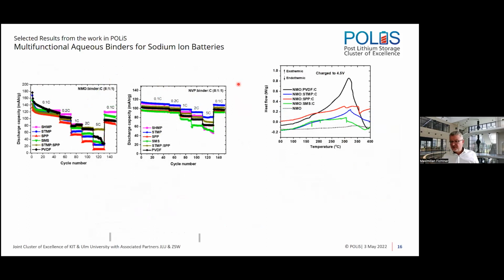An activity which was related to that was the development of new binders, because binders can play an essential role in the performance of batteries. And what we did here was to develop multifunctional aqueous binders for sodium-ion batteries. Multifunctional in that they do not only bind the materials, do not only glue them together, they also have a certain sodium-ion conductivity. So if they are binding the materials, still the sodium can enter or can be taken up from all the different facets of a crystal. And this is something which pays out.